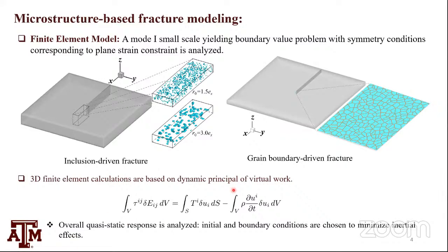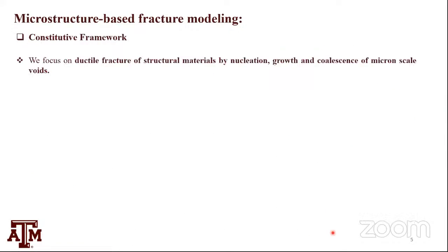And since we're doing dynamic calculation, but we're interested in quasi-static fracture, we apply initial and boundary loading conditions such that it minimizes inertial effects, which is basically the wave effects. So we got the method, we got the model. Now we need the constitutive method.